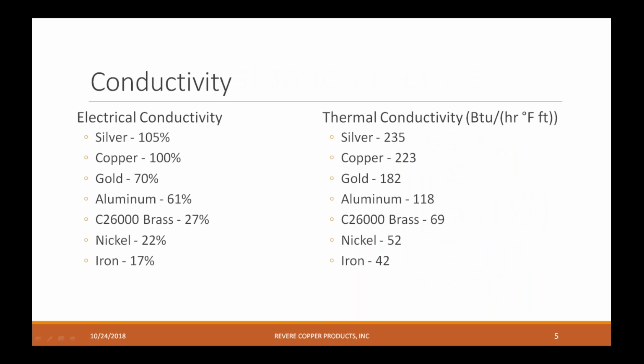So here's a comparison. You can see the electrical conductivity of silver at 105, copper at 100, gold at 70. Those three are pretty close. And there's a significant drop when you get into aluminum and go all the way down to iron at 17%. And then thermal conductivity, you'll see copper also very similar to gold and silver. And then you see a drop for aluminum and then all the way down to iron.